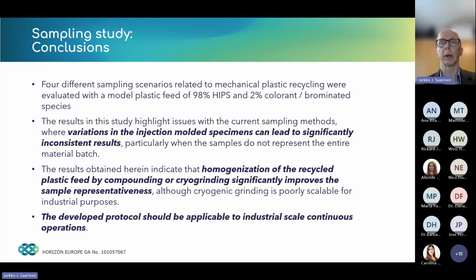The main message to carry home here is that if you just use injection molding, making the dog bones, that is an insufficient manner of doing representative analytics of the whole stream. The variations in the injection molded specimens can lead to significantly inconsistent results. The samples do not represent the entire batch, but depend more on which flakes happen to be within that stream while making the dog bones.